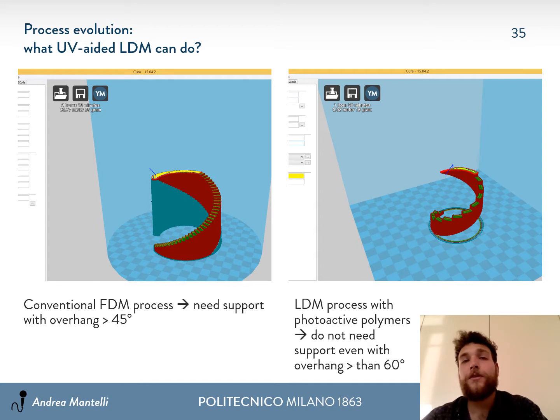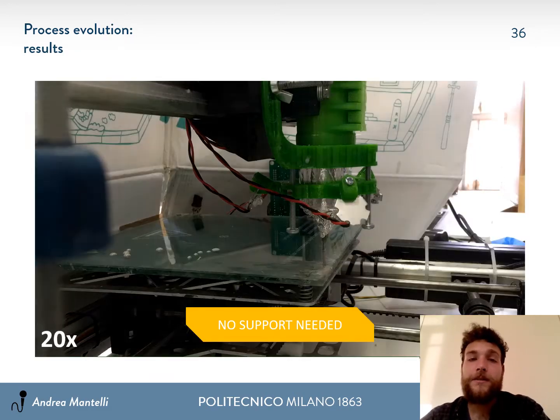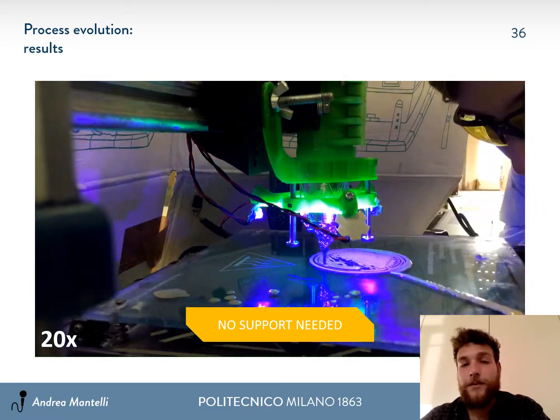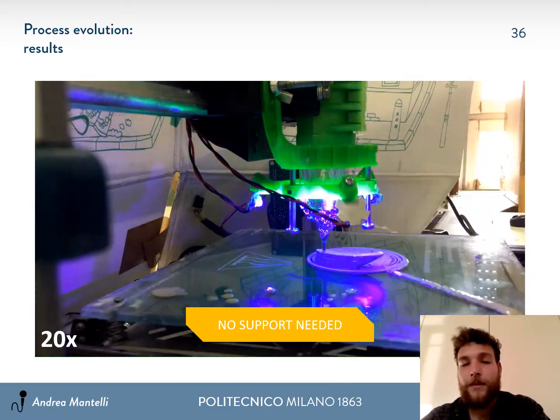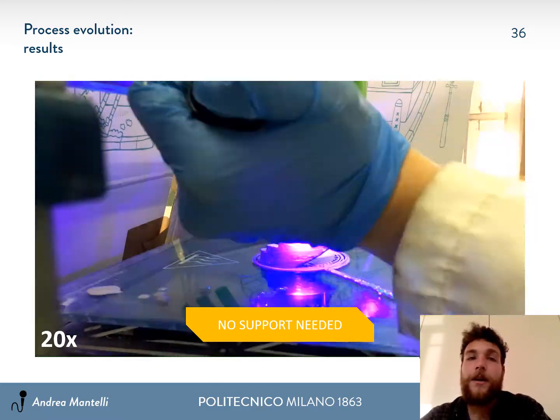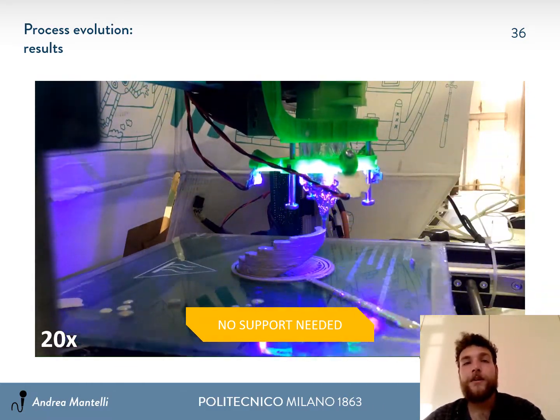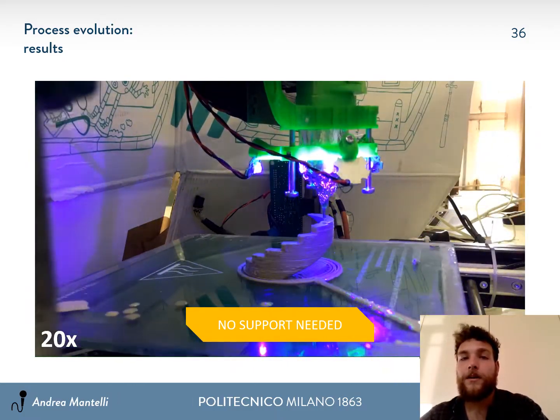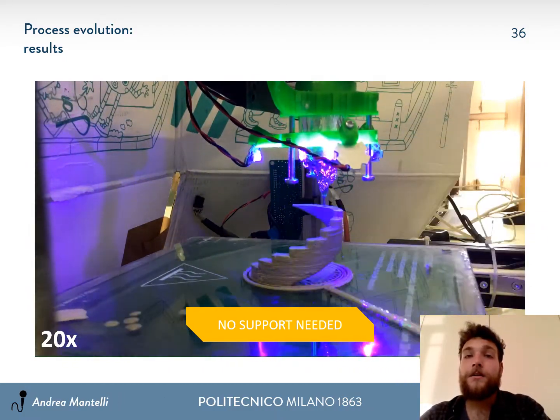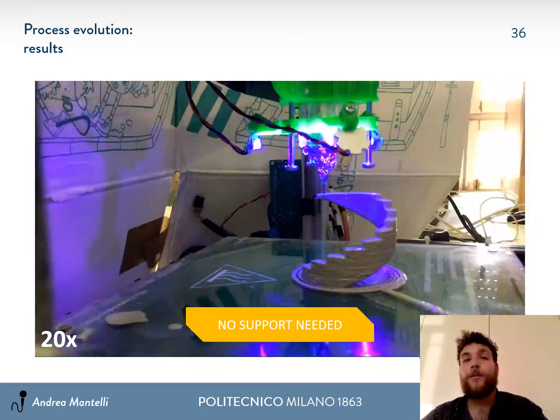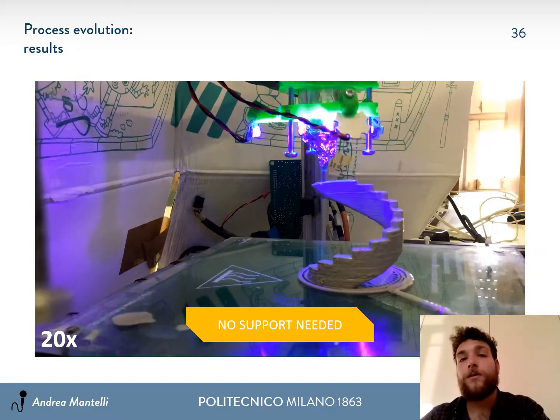One of the main features of UV-aided 3D printing is the possibility to print without supports, even when they would be needed in the FDM 3D printing process. In this video, you can see that the 3D model, which is a kind of spiral, grows up without support, and the angle between the building plate and the overhang surface is lower than 30 degrees. This is possible because the material is rapidly cross-linked as it goes out of the nozzle.